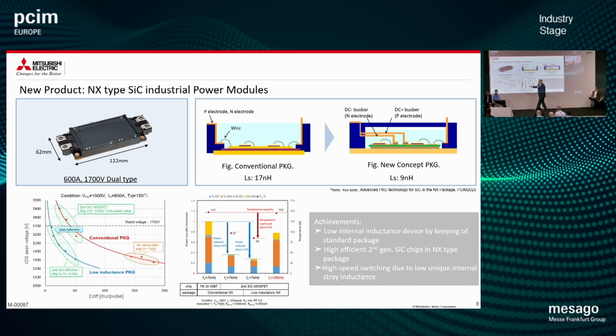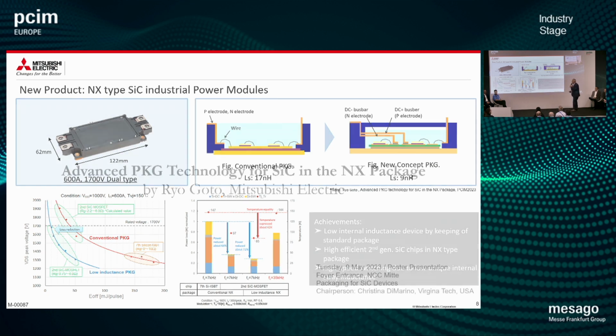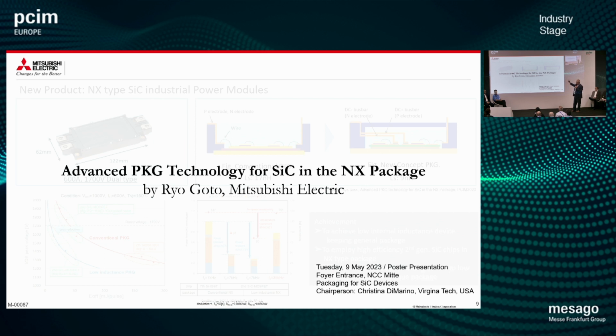Results are here. Without touching the chip performance, we reduce switching energy by half just by introducing a new packaging technology, and we respect the safe operating area and reduce switching energy. Result is here. This is silicon carbide in a non-compensated or traditional package. We see approximately 75% here, and just by introducing our new package, we see higher efficiency, meaning 85% lower losses. The result of this investigation is now under discussion in the lobby of PCIM. This is a poster session presented by Mr. Goto and managed by chairperson Cristiana De Marino, chairlady.